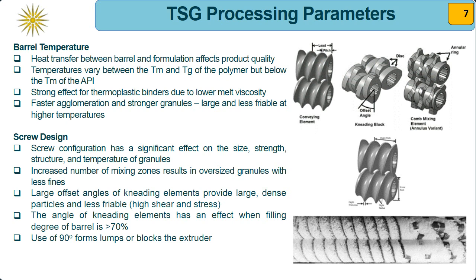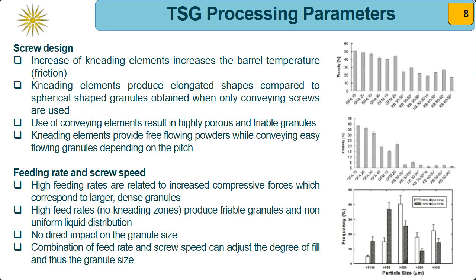On the right image, we can see a representation of different screw elements with some conveying elements and kneading blocks with different offset angles. These elements can be used in combination during the granulation process, and we will see later how the quality of the products can be controlled. The increase of the kneading elements increases the barrel temperature due to the created friction, and it has also been found that kneading elements produce elongated shapes compared to the spherical shaped granules we obtain when we only use conveying screws. The use of conveying elements results in highly porous and friable granules.